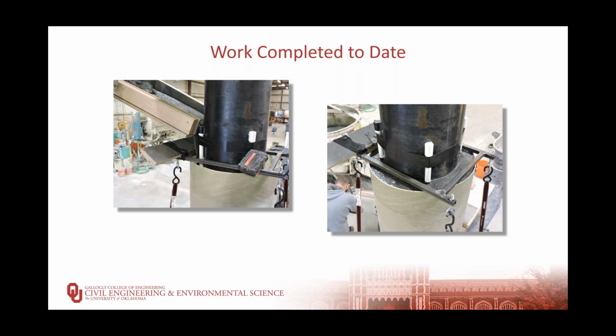We also poured the ultra high performance concrete into 2 of the specimens as well. This material also flowed very well. It has a 28-day compressive strength nearing 20,000 PSI, and it's the non-proprietary UHPC mix that was developed and tested as part of some earlier ABC UTC research studies. Again, this flowed very well through the 8-foot tall column, causing no segregation and no voids, and did not require any internal or external vibration.